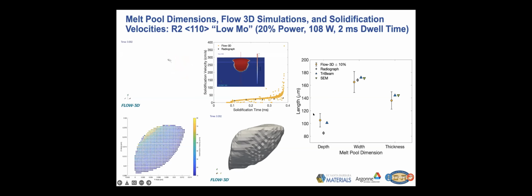Here, we're also comparing the characteristics of the melt pool. We have length versus melt pool dimension for the width and the thickness and the depth. Here, we're comparing our Flow 3D simulations to our radiography, in addition to our 3D tri-beam to just 2D SEM. And we do a really nice job with width and thickness of the melt pool. So again, that shape of the melt pool has to match in our simulations. Depth is a little more off. This is associated, we believe, with our experiments that we did at the APS and sample alignment and things like that. So there's a little more wiggle room in the depth. But nonetheless, now we can one-to-one ground what we're seeing experimentally with the modeling.